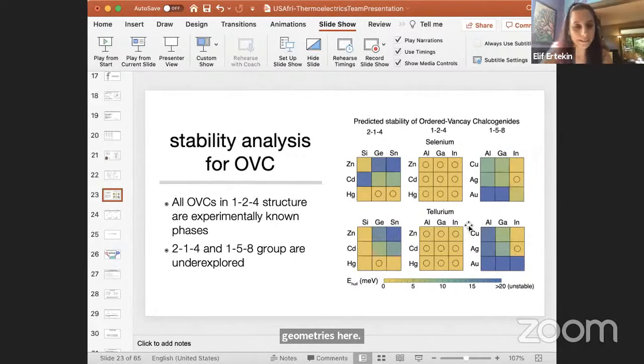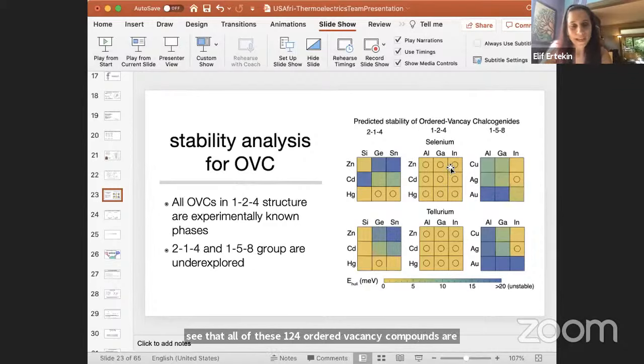And then the color bar indicates the distance to the hull that we predict for the material. So anything that's yellow is a compound that's predicted to be on the hull or stable. And the more blue it gets, the more likely we believe it is not going to be a stable compound. So if you look at this, you'll see that all of these 1, 2, 4 ordered vacancy compounds are predicted to be stable. And in fact, these circles here mean that the chemistry is an already experimentally known or reported chemistry. So in this case, all these 1, 2, 4 compounds are predicted to be stable, and in fact, they're experimentally known. And then meanwhile, the 214 phases and the 158s, we've rediscovered some already experimentally known phases, but then we also predict a few more to be stable that have not yet been reported. So it may be the case that some of those families are somewhat underexplored.